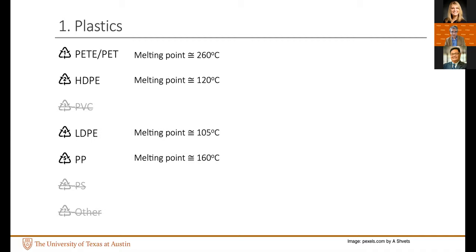One other interesting thing that I want to point out here is that if you look at the melting point of these four plastics, PET is the highest, which is about 260 degrees Celsius. The others are 120 to 160 degrees Celsius, which means that in terms of mixing or repurposing this with asphalt mixes, PET is a better candidate for a dry mix, meaning I'm using the same terminology that is used with asphalt rubber. A dry mix is something that is added during mixture production, and a wet mix is something that is added to the binder. It becomes a part of the binder matrix, and then that binder is used with aggregates to produce a mix. So if you look at PET, that is a better candidate for a dry mix because the melting point is so high.